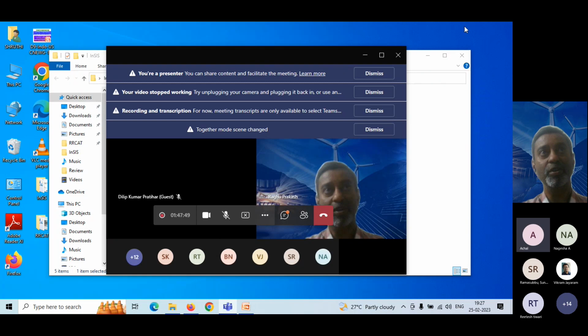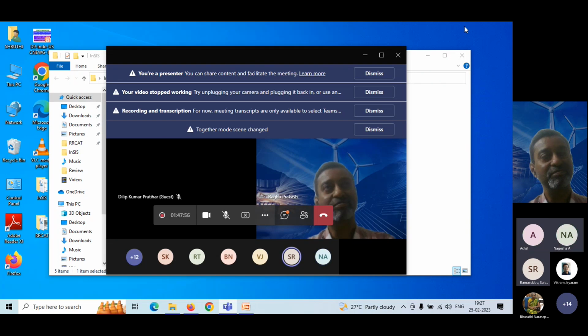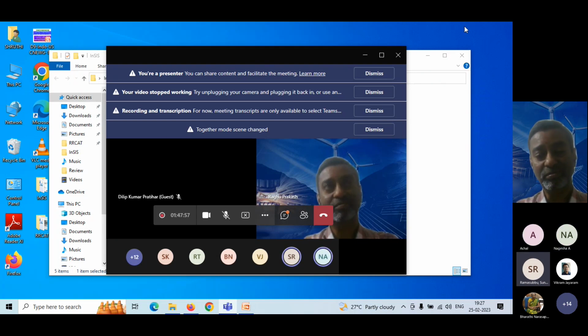Oh, you mean like program the waveform for TMF and then study it? Not the waveform. For example, on the equipment, you have a couple of cycles with TMF and then a couple of cycles at lower temperature just to mark the crack, without affecting the damage process, and then get back to thermal cycling and then look at the result over there on the fracture surface.